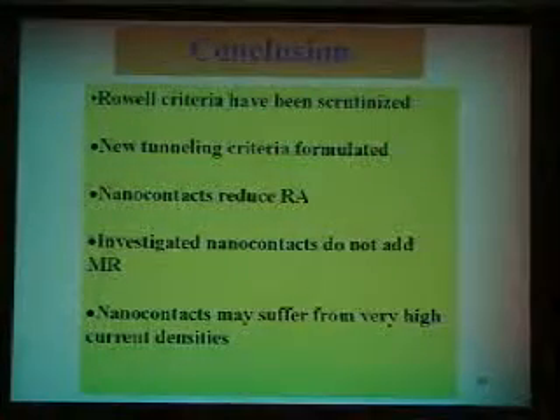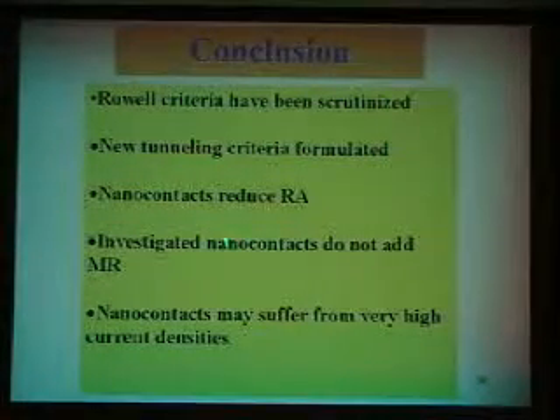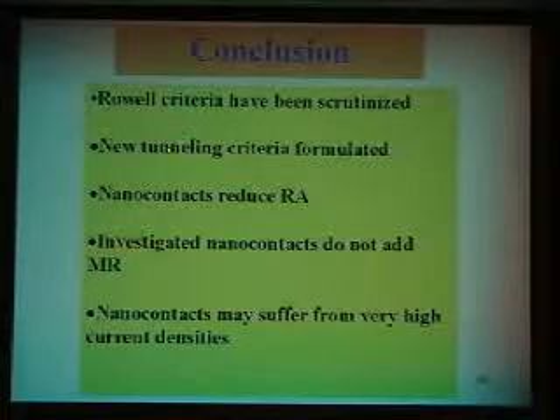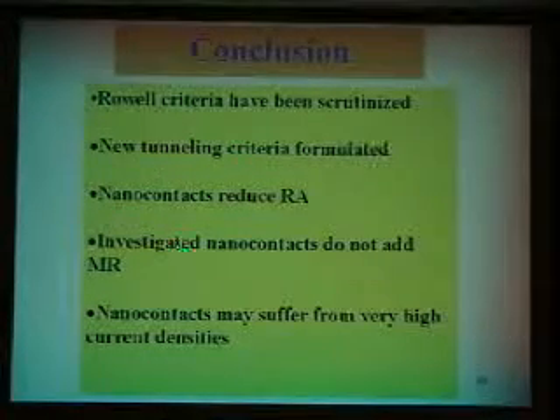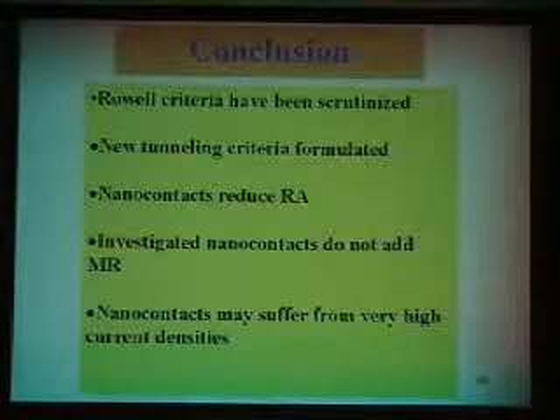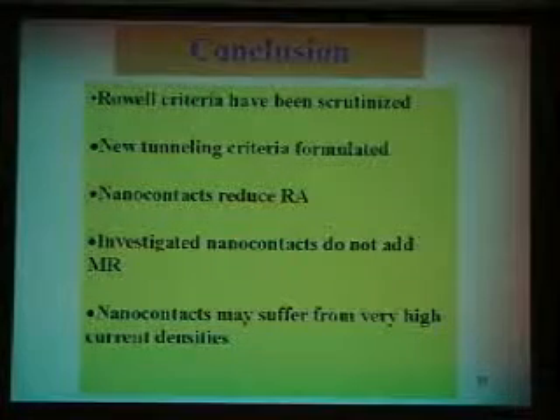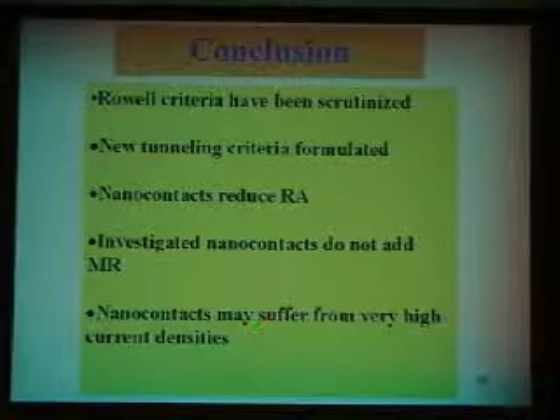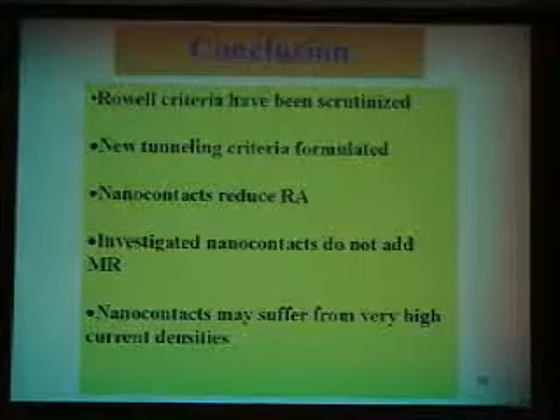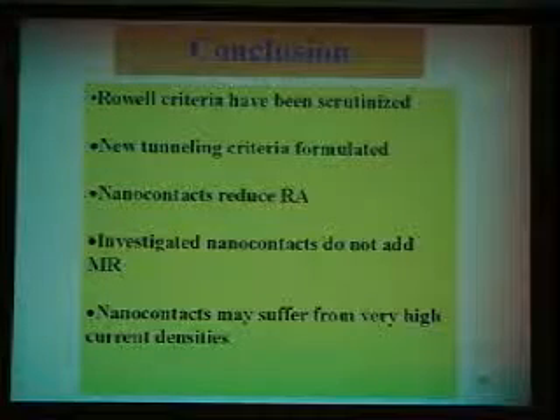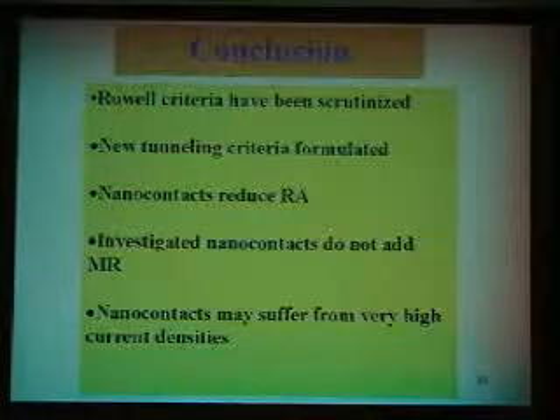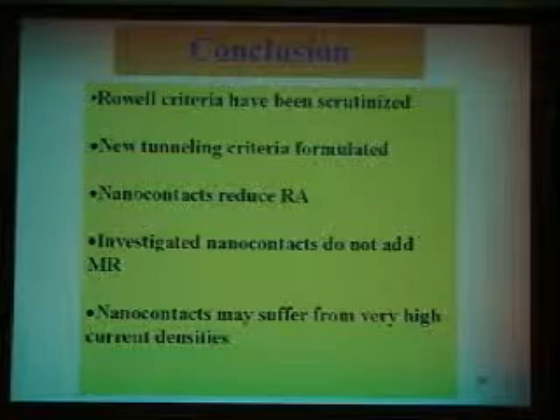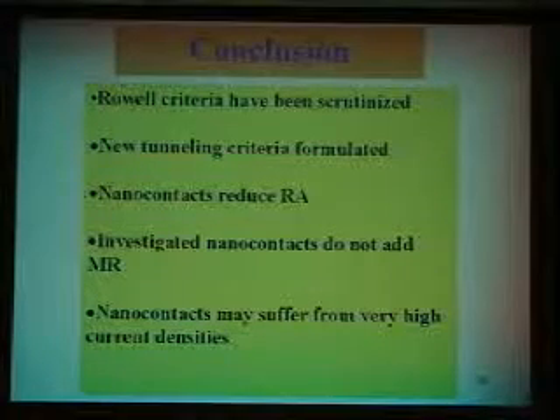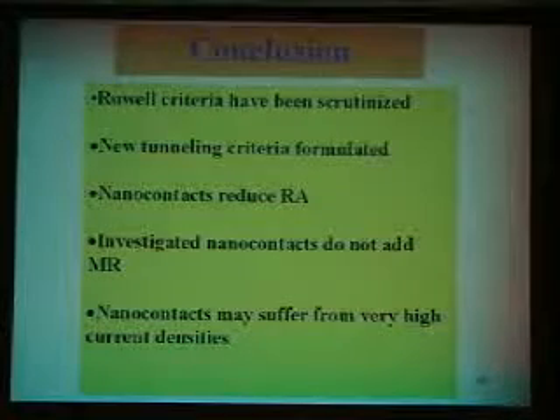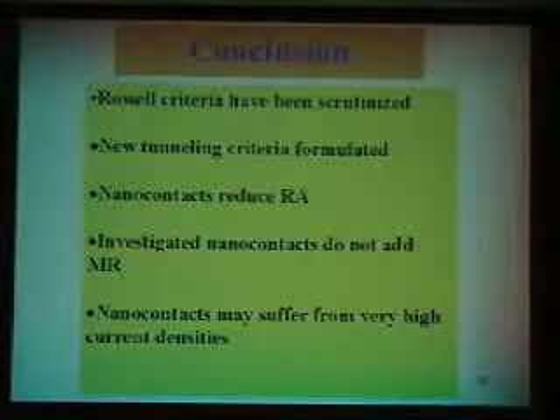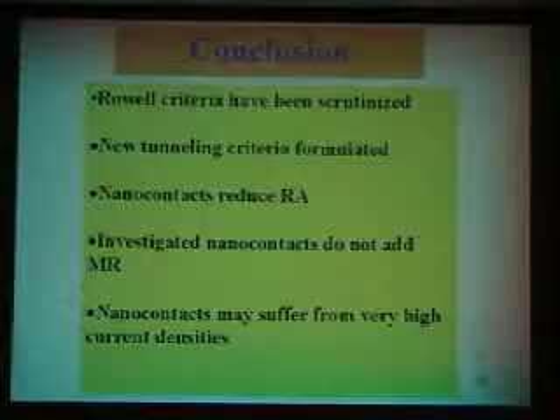Okay, so here is the conclusion of what I told you so far. I told you that we looked at this, that the new tunneling criteria were formulated, and the nanocontacts reduce the resistance per area as you expected. And then we investigated nanocontacts and found that they do not add any magnetoresistance, and they may suffer from very high current densities if you have a very thin contact there. And that's actually important even for this ballistic magnetoresistance, independent of this, because you put a current through this. Think about it. You have 10 to the 10 amps through something. That's a huge current.